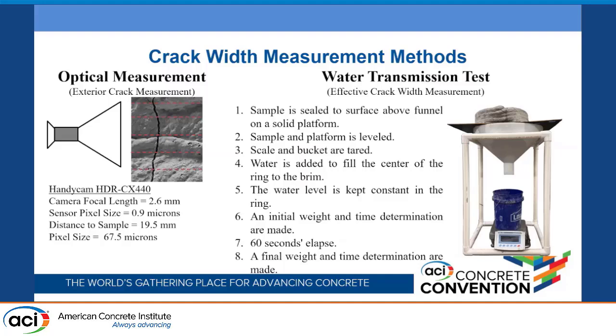We did an optical measurement of our crack widths. That was pretty simple, using a high-definition camera to get a precise photo of our samples, achieving a pixel size of approximately 67 microns, then converting that picture into grayscale and using image analysis to calculate the crack widths across the sample using scan lines to create an average value.